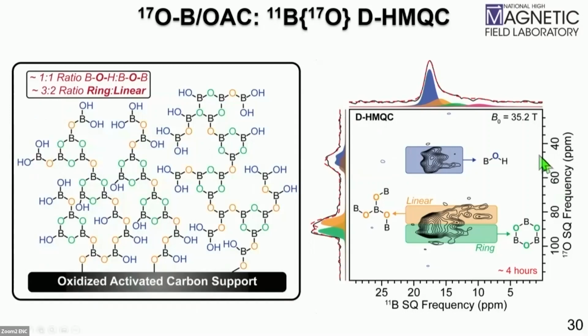Now from the HMQC, we can see that the most intense boron NMR signal, which corresponds to about 80 to 90% of the boron, correlates to all of the oxygen NMR signals, the hydroxyl groups and both types of bridging oxygen atoms. So it's confirming that they're homogeneously distributed throughout this layer.